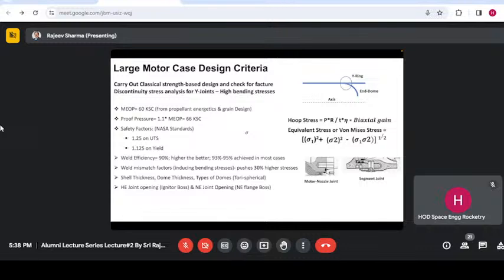One thing was that the domes in those days were made with a forming process, which was a very well-defined process by Walchandnagar Industries and other larger players. When you form the dome from a starting thickness, it becomes thin. There is what is called thinning of the dome, especially towards the igniter boss area. And we had to cater for that.